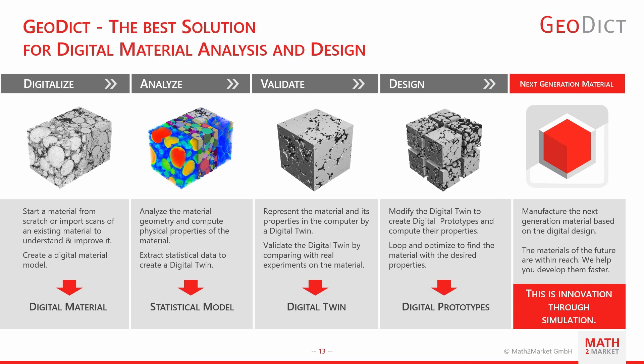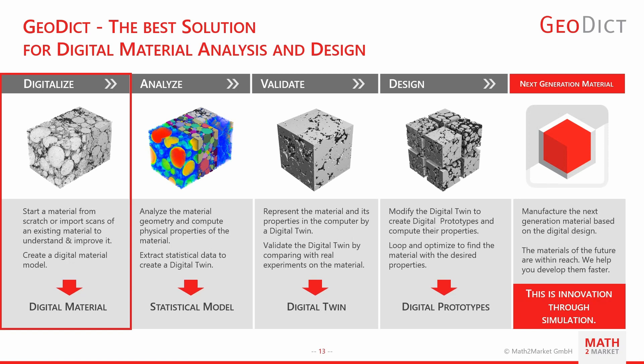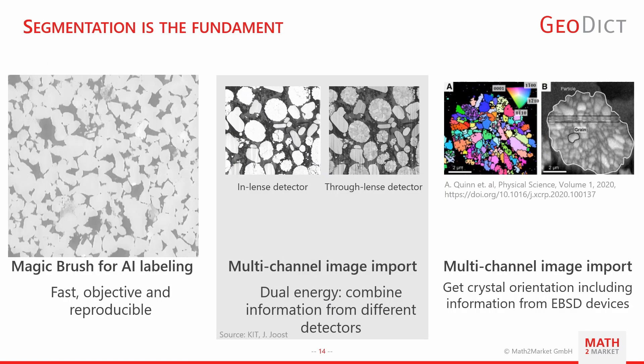The typical workflow for digital material design with GeoDict starts with a digital model of the microstructure. You can import grayscale CT or FIB-SEM images, then segment them using grayscale values or AI segmentation. For AI segmentation, you label images to train the model. GeoDict now includes a 'magic brush' feature to help label grayscale images faster.